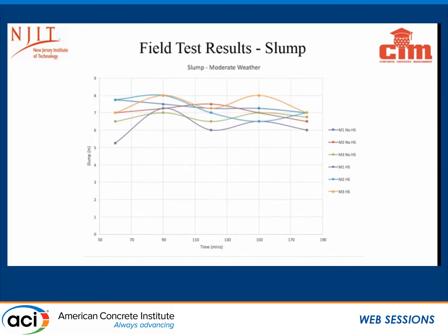And here we have the same in moderate weather. The first one previously was in hot weather, and these mixes we started in about August and went down to October, to give you an idea again of realistic field conditions. Again, you have fairly consistent slump retention, especially using the hydration stabilizer admixture.